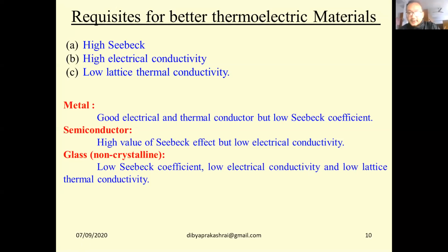So, if you see this one, where will you find the high Seebeck effect, where will you find the high electrical conductivity, and where will you find the low lattice thermal conductivity? Metals are good electrical conductors, so electrical conductivity is very high in metals. Charge transport is governed by the Wiedemann-Franz law, so at the same time the thermal conductivity will also increase. The electron part of the thermal conductivity will also increase, but the metal will definitely have a low Seebeck coefficient.